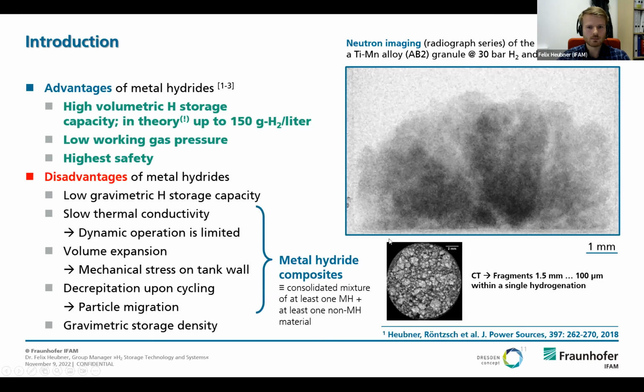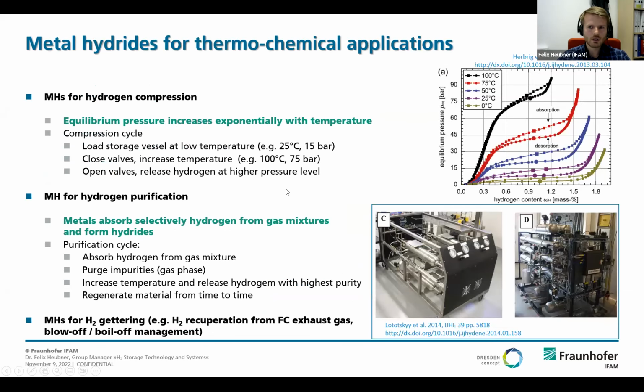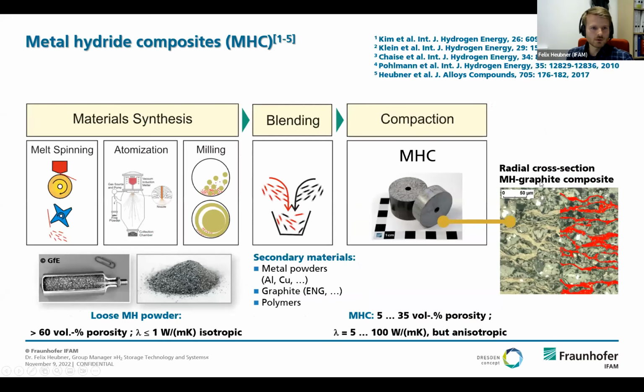So one solution is using metal hydride composite materials. I will skip this slide here. The composite materials use as a basis a metallic powder, or a powder that is able to absorb hydrogen. A second phase is needed to increase the thermal conductivity of the powdery material of the first one. So both materials are mixed, blended together, and compacted afterwards in a uniaxial press to such a kind of tablet. These tablets now have increased thermal conductivity of, let's say, 5 to 100 W/(m·K), and a reduced porosity of the powder as well. So it's easier to integrate these tablets into tube bundle reactors that are made to store hydrogen.